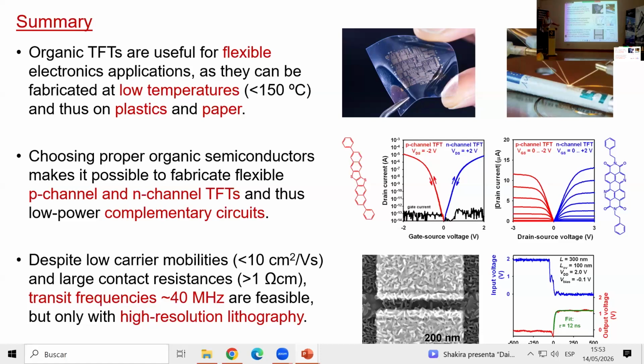And despite the fact that the charge carrier mobilities in organic semiconductors are extremely small, as you know, on the order of 1 centimeter squared per volt second, as you've seen, and despite the fact that the contact resistances are much larger than in silicon MOSFETs, it is possible to reach transit frequencies on the order of several tens of megahertz, but only by going to the nanoscale regime. Okay, so as long as the contact resistance is on the order of tens or hundreds of ohm centimeter, it will be necessary to make the transistors with nanoscale dimensions in order to achieve the kind of transit frequencies that we're aiming for.